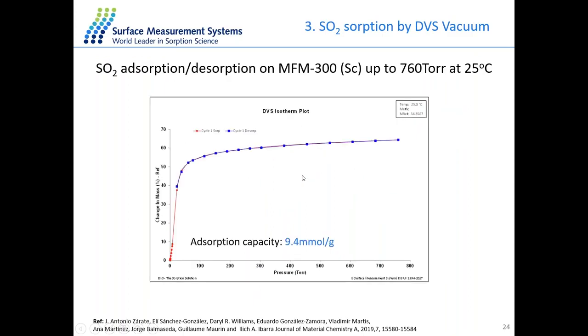And here we'll give you the isotherm of this MOF material. It's a very nice type 1 isotherm for the microporous material. And the adsorption capacity for this MOF material is about 9.4 millimole per gram.